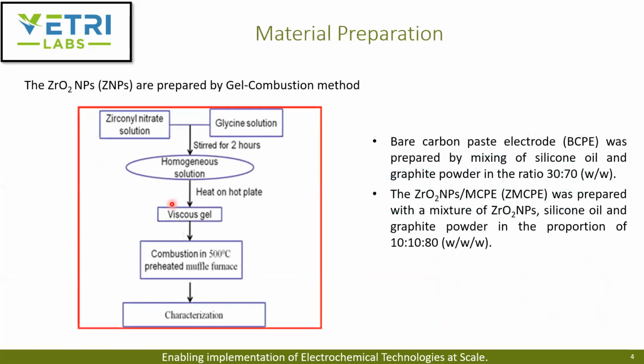In this paper, they did the material preparation using the gel combustion method. In this, they used zirconyl nitrate solution as an oxidizer and glycine as a fuel, and used a minimum of water and stirred it for 2 hours to form a homogeneous solution. Then they heated it on a hot plate to evaporate the extra water so it can form a viscous gel. Then they transferred this viscous gel into a muffle furnace that was already preheated to 500 degrees Celsius. Since this viscous gel is flammable, it catches fire and combusts, and at last it forms white fluffy nanoparticles, which are the zirconium oxide nanoparticles.